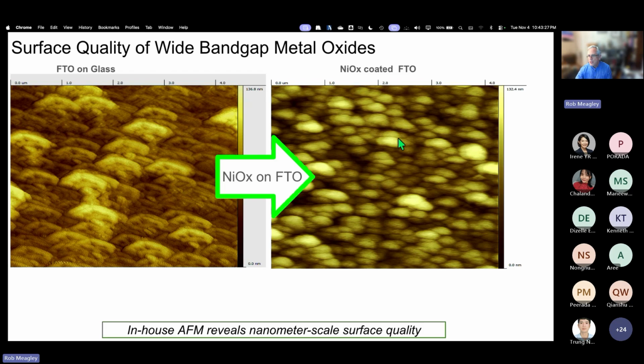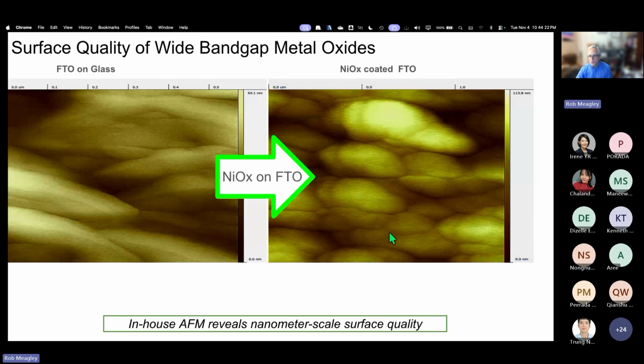And the nickel oxide, you can see, is covering over some of the topography, and yet you are able to see again some of the facets showing their nature, and we could diagnose both the surface quality and the coating consistency of these substrates. And we'll be looking at some other related materials, and you'll see exactly what I mean, because not all nickel oxide coatings are as uniform as others. Again, I stress that being able to examine quickly and efficiently across many different kinds of materials is very important when understanding incoming material quality, process quality, or comparing one process to another in terms of coverage or surface consistency.